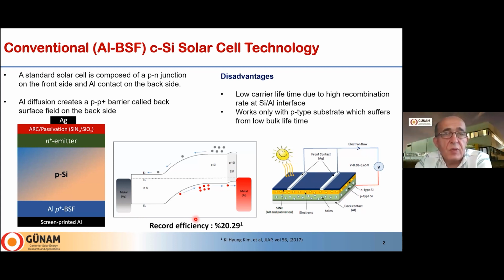The record efficiency for this structure was slightly above 20%. And the major disadvantage in this structure is the low carrier lifetime at the backside, due to the high recombination at the backside, because this aluminum silicon interface is not good for the carriers. They are acting as high recombination centers, so that you lose the generated electron and hole pairs due to this recombination. So this is the major drawback of this type of standard traditional solar cell.